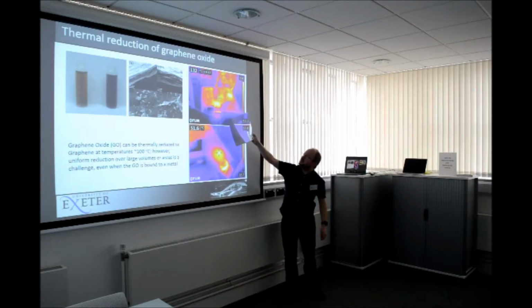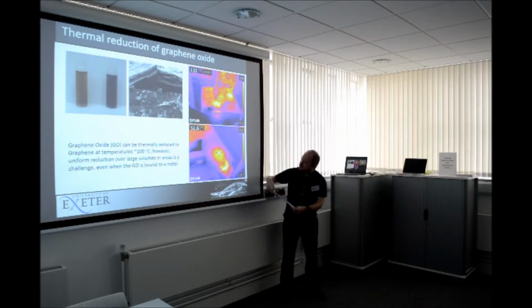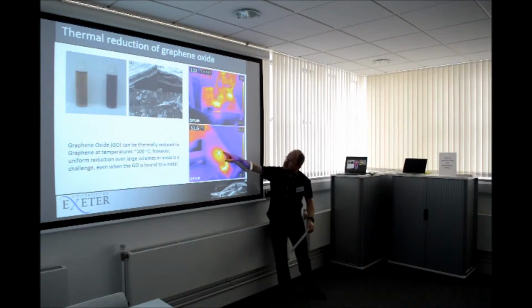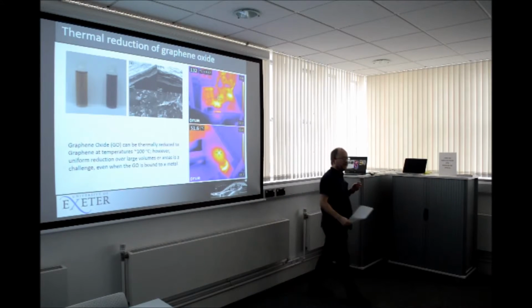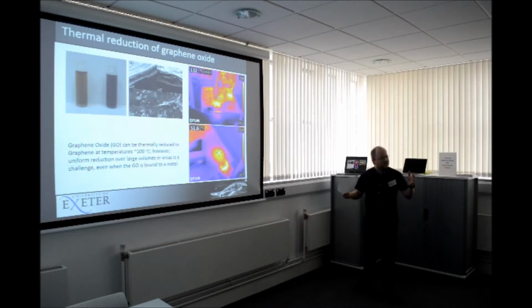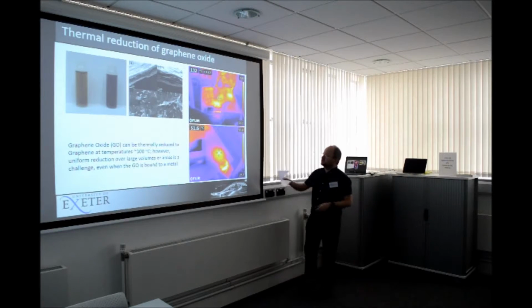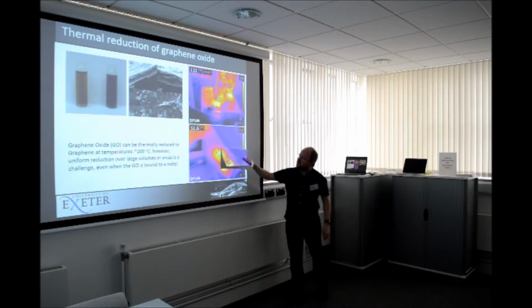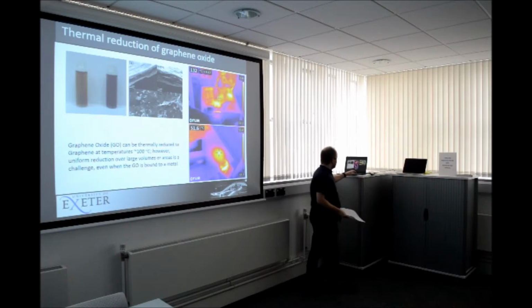This is a 1 meter square sheet of metal. And he was trying to heat it with various little hot plates. And you can see that the heat is very localized here. It's very tricky to start building up onto larger and larger scales. Any sort of graphene layer tends to be very localized. So that was something my postdoc did.